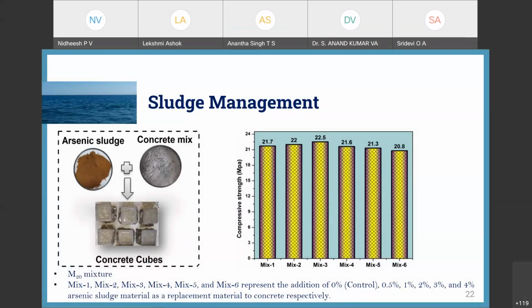Then, as I mentioned, the sludge containing arsenic and its disposal is also an issue. So what we proposed and had done is what we call stabilization and solidification of sludge. In concrete, we added some percentages. We used M20 mixtures, and different concentrations of arsenic were added. That means 0% is mix 1, mix 2 is 0.5% arsenic sludge, and we found the compressive strength. These experiments were carried out at NIT Raipur.